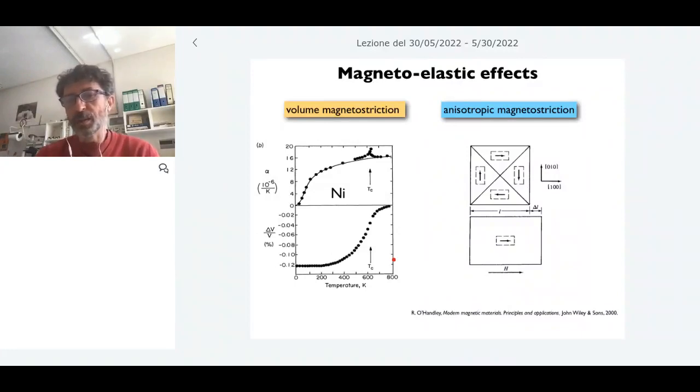So it's around 0.12% in the full change of temperature. So not that large, something small. But there exists a correlation. So in the specific case of nickel, you will have that in the paramagnetic state, the cell itself will tend to be larger than in the ferromagnetic state. Well, it expands a little bit more because it also becomes disordered.